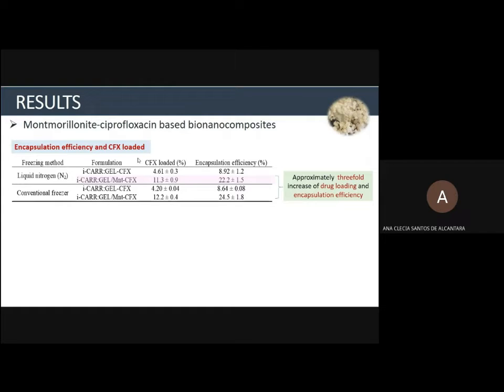in both cases. This fact could be associated with the possibility of slower diffusion of some drug molecules from the interlayer region of the silicate, contributing to the good affinity between the montmorillonite and the biopolymers used in the present study. However, it is important to highlight that there are no significant differences in the drug loading and encapsulation efficiency values between the bionanocomposite samples frozen through conventional or liquid nitrogen freezing methods. But this behavior is expected since this drug incorporation process is performed prior to the freezing step. Then, this process should not have any influence on the amount of the encapsulated drug.